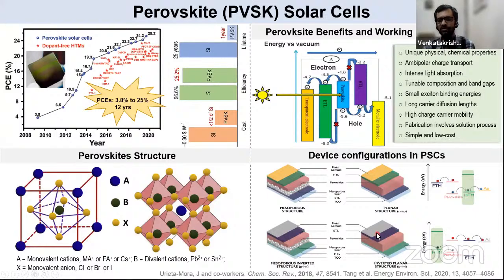What is more important to us in this center is to focus mainly on the hole transporting material. The job of the hole transporting material is to extract the holes and then pass them on to the electrode actually. So there is a lot of interest in developing novel hole transporting materials because this seems to be the layer that is sitting on top of the perovskite, particularly in the NIP device configuration, where this prevents the moisture entering into the perovskite and provides some kind of stability against perovskite decomposition.